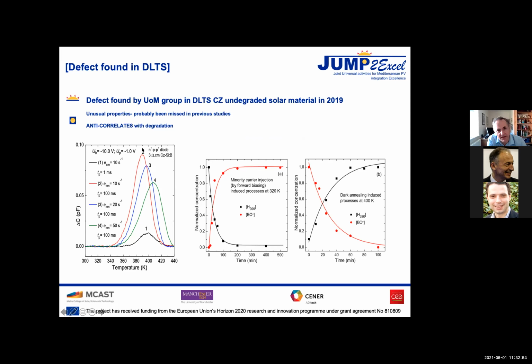But why do we find this? Nobody else has. The answer is it's a high temperature, and it's unusual. And we think no one's looked. That's all. It's as simple as that. We just think that nobody's looked for it before, at the right temperature range and the right pulse range. DLTS is pretty much the standard way to look for traps, and so it would have been looked at many times. But indeed, it has been looked at by us many times to try and find it. But probably people just didn't go to a high enough temperature. Simple as that. So we found this defect, but it has some strange behavior.